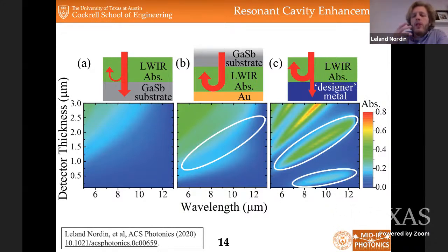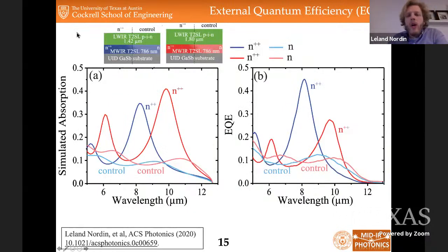But to actually demonstrate this, since this is all simulations, we grew 2 detectors on top of N++, and then also 2 control structures targeting 2 enhancement wavelengths, one at 8 microns and one at 10 microns. Shown at the top are the actual structures, they're just PIN optoelectronic devices, and then shown below is both our simulated absorption for the enhanced devices and their controls, and then our actual experimentally measured external quantum efficiency.